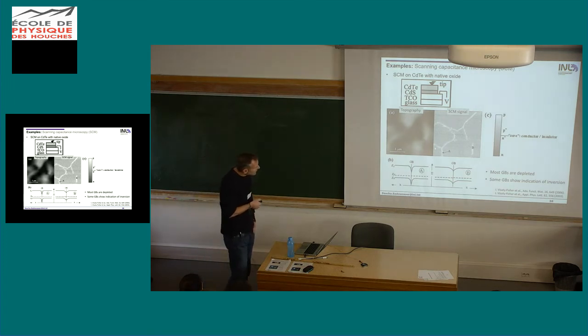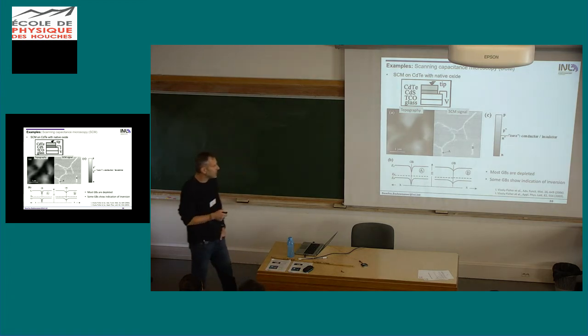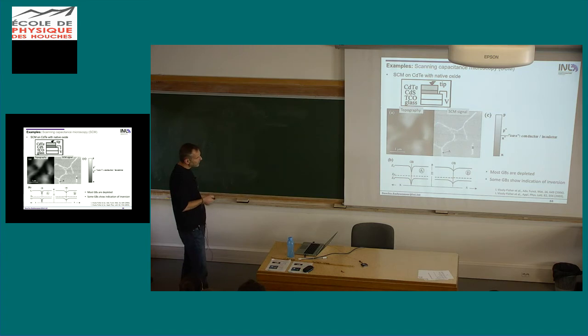But they also observed here some cases where it turns dark. So just in the middle of the grain boundary there's a very thin dark line, and they interpreted this by an inversion. So here actually we go into a case where at the grain boundary we have an n-type material. So the bands are so far bent down that the type changes and it becomes n-type.